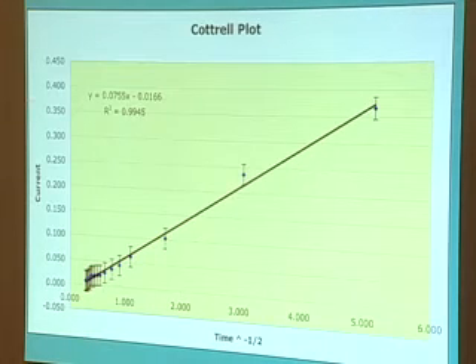There's the current as a function of time to the minus 1/2 power, and there's the fit to the line. You can see that we have an r² value of 0.99 plus. So that should convince you that, in fact, the Cottrell equation works. And quite obviously, if I was interested in the diffusion coefficient in this system, for example, I could extract that from the slope of this line, again assuming I know what n is and what the concentration is, and the area of the electrode. Okay, so that's one approach that we can consider.